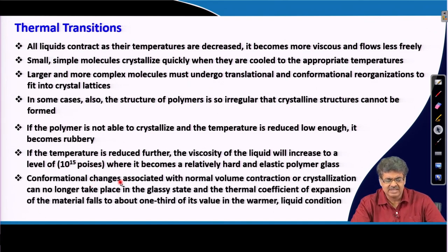And in this case, the conformational changes associated with the normal volume contraction or crystallization no longer take place in the glassy state, because there is no freedom at all. So, the conformational changes and volume contraction because of further decrease in temperature do not happen. So, the thermal coefficient of expansion of this glassy material falls to about one third of the value in a warmer liquid condition, because the molecules are large and almost in a frozen state, they don't have any mobility, so it cannot contract during decrease in temperature. So the coefficient of thermal expansion for these glassy materials falls to about one third of its value compared to the warmer liquid condition.